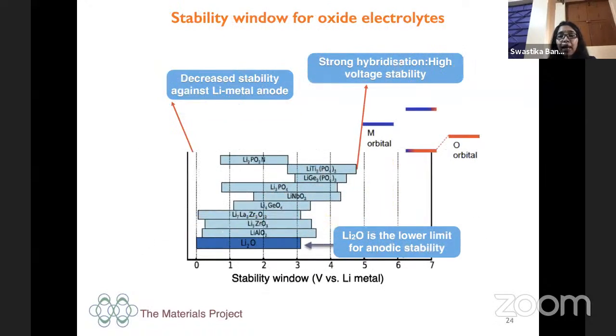So if we look at the other thing, the anodic side, we find the oxide-based systems are really good in terms of anodic stabilization in comparison with the sulfides. So it also depends on how strong the hybridization is and on the voltage stability. Actually, there is a lot of chemistry I can discuss with you in detail, but time is very limited. For this stability window, what dictates the oxidation limit or the reduction limit is very basic. You can think in terms of molecular orbital theory: how the hybridization or the exchange happens, and how easy the redox process is, depends purely on the bonding pattern of the system.